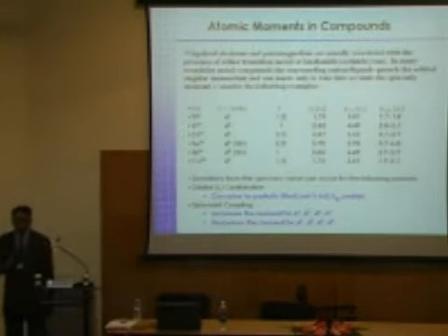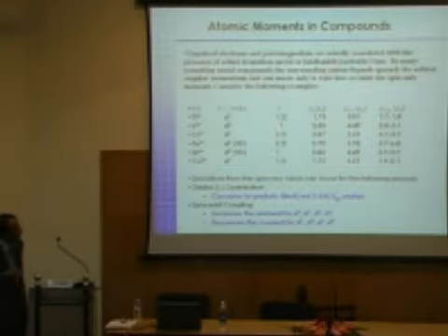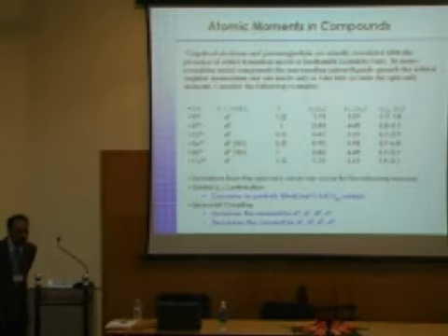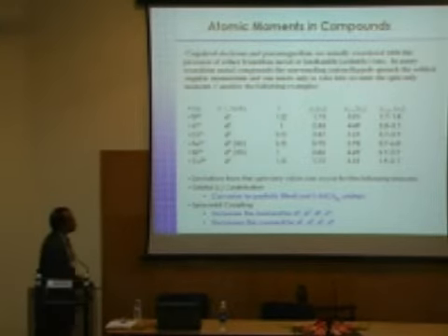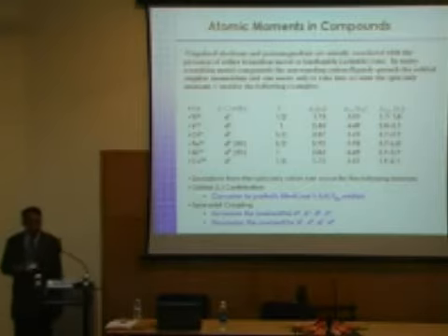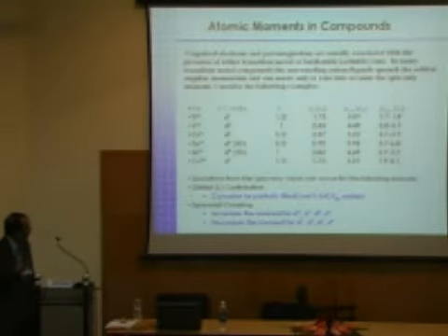But experimentally, titanium 3+ always gives magnetic moments in the range of 1.7 to 1.8. So what does that tell us? Does the orbital moment contribute to the magnetism or no? No. So clearly I see one head saying no. Yes, in the case of titanium, the magnetism is purely the spin contribution only. There is not much of magnetic contribution from the orbits.